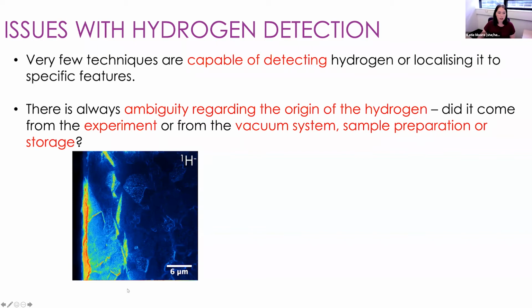But we can also see over on the left-hand side, we've got this somewhat smudgy region of hydrogen that's a little bit more difficult to explain. So did this hydrogen come from the interaction of this metal with the conditions in the autoclave where this sample was oxidized, or is it an artifact?